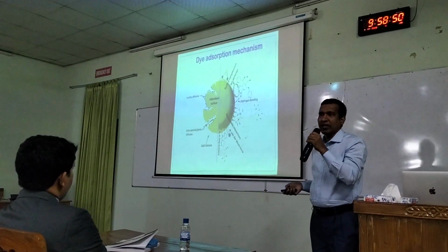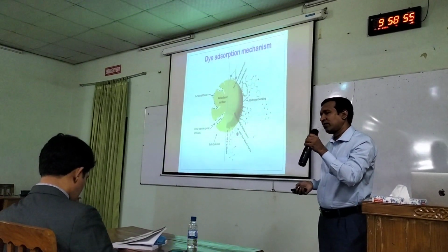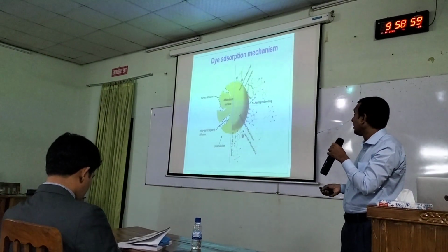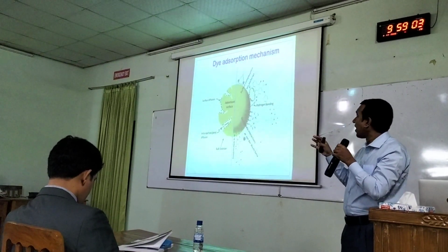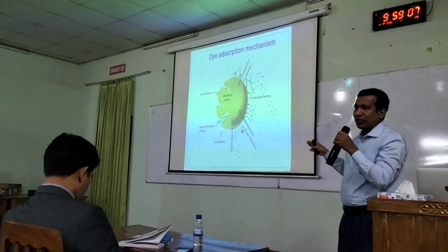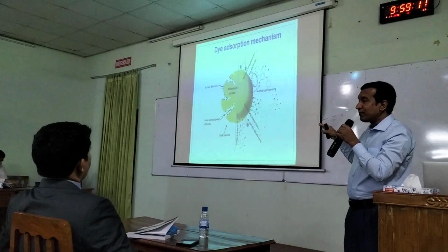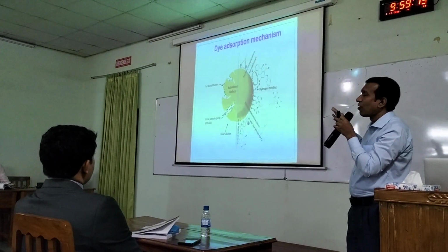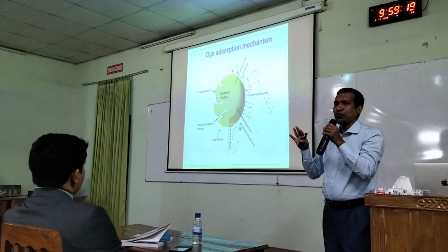So from our study and previous literature, we introduced a mechanism of dye adsorption. Dye molecules adsorb onto the surface by electrostatic interaction, van der Waals forces, hydrogen bonding, intraparticle diffusion, and most importantly, surface complexation. Surface complexation involves two forms.